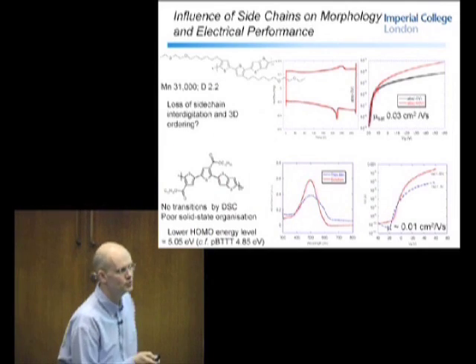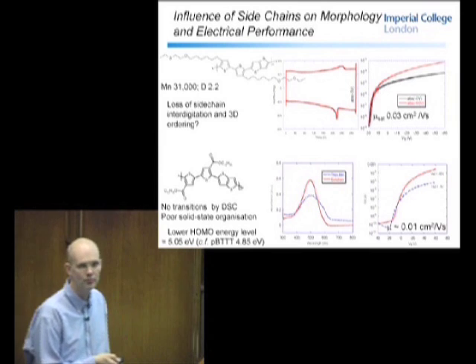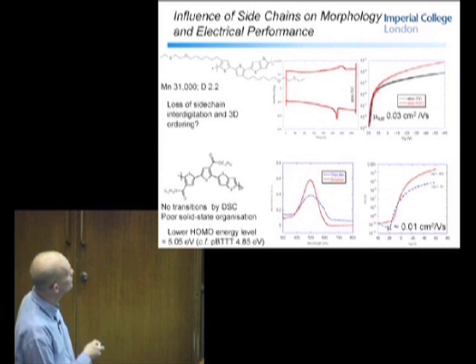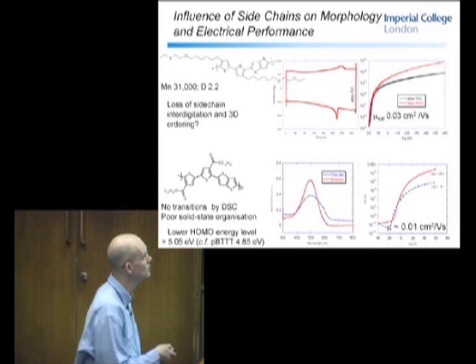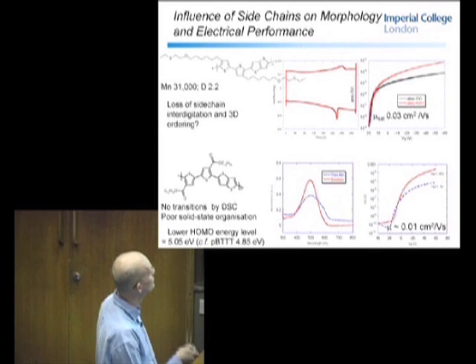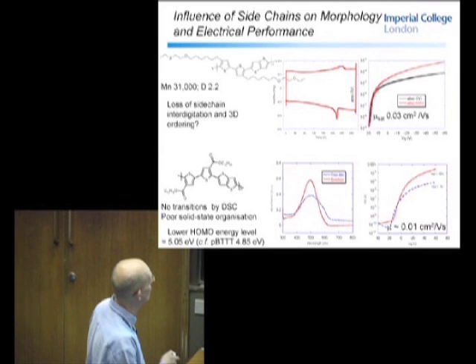One of the big problems with polymer semiconductors is solubility, and unfortunately everything we try to do to improve the solubility has an adverse effect on the performance, and this is a sad tale as shown in this slide here. You reduce the order of the material, you do improve solubility. In this case we're also trying to improve the ambient stability by lowering the HOMO energy level, but again performances were never that great.